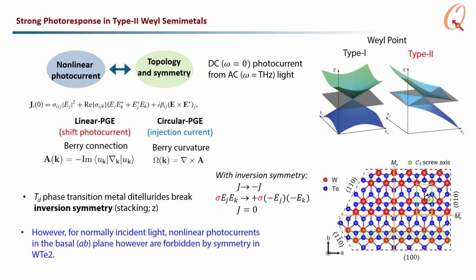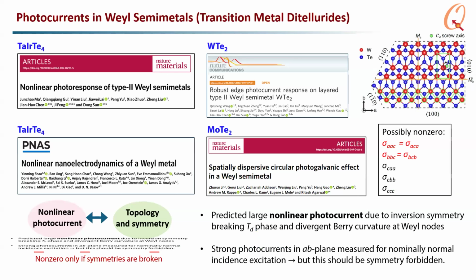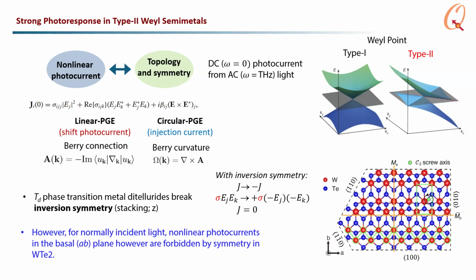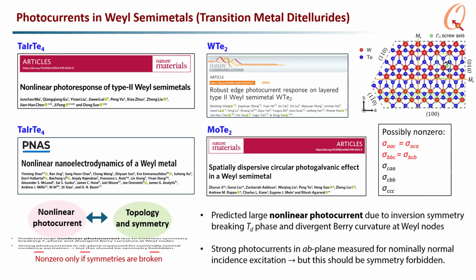But the problem was that the photocurrents people were measuring were in the AB plane for light that was nominally normal incidence. Because I have these two mirror planes in the AB plane, I shouldn't get nonlinear photocurrents if I just have normal incidence. That's because the nonlinear susceptibility tensors are non-zero only if you break certain symmetries. For these Weyl semimetal transition metal ditellurides, the only ones that are possibly non-zero involve the C-axis. So either the light has a component along the C-axis, or the current is along the C-axis.